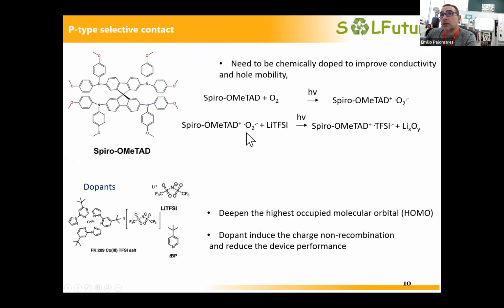So the idea was, well, here are the processes that, for example, people like Saif Haque have studied quite a lot at Imperial College about the degradation of the perovskite solar cells, and they come out with this hypothesis that you oxidize the Spiro-OMeTAD with the salts, and then you also need to have dopants. You really want to have high efficiencies, but the presence of dopants also makes the cells unstable. So it's kind of a compromise. You want devices with long lifetimes. You don't need to use dopants, but then your device efficiency is rather poor.